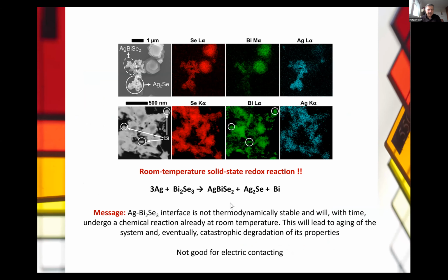We also went back to the powder and inspected it under SEM. We have done mapping, and we've been able to see again the product, identified silver bismuth selenide, silver selenide, and we have also found some metallic bismuth particles present. So here again, all that was done at room temperature, and we are able to write down again one